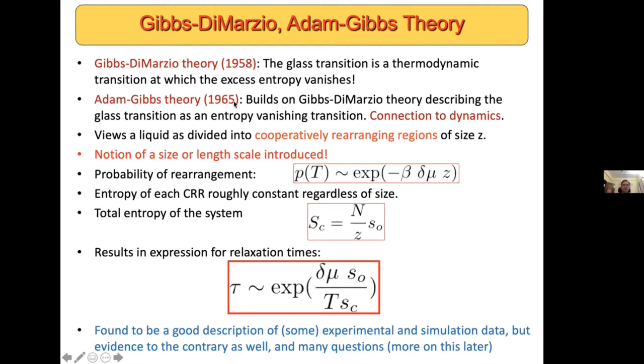And Adam and Gibbs built on this Gibbs-DiMarzio theory, describing the glass transition as an entropy vanishing transition, and made a connection to dynamics, or the slowdown of dynamics that one observes in glass forming liquids. And the basic idea is that as I go to lower and lower temperatures, there is a certain size of what are called cooperatively rearranging regions that grows, that becomes bigger and bigger. And the meaning of these cooperatively rearranging regions is that if I were to take any sub volume of that region and constrain the system outside to remain as it was, this sub-volume will not be able to reorganize. So there's a minimum size of participating particles that is necessary in order for